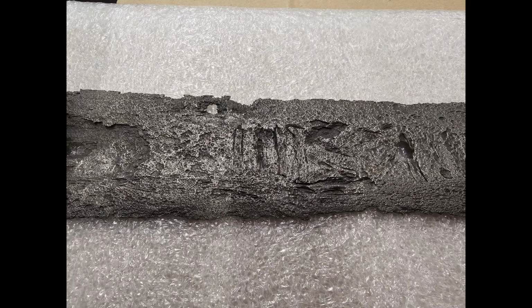Although the edge steel also has a layered appearance, there is no indication that 2 types of iron or steel were used, but it has more the appearance that the same bar of steel was refined by folding and welding it back on itself several times. Also, the chemical analysis of different spots over the sword of the edge steel show that they are very uniform in composition.